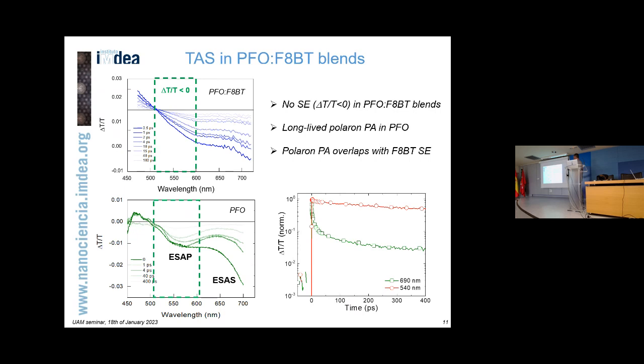This longer decay is caused by the fact that in the film we are generating also charge transfer states. So the original neutral states dissociate because they found lower energy sites where they can separate, in what we call a polaron pair. And this has a much longer kinetics.